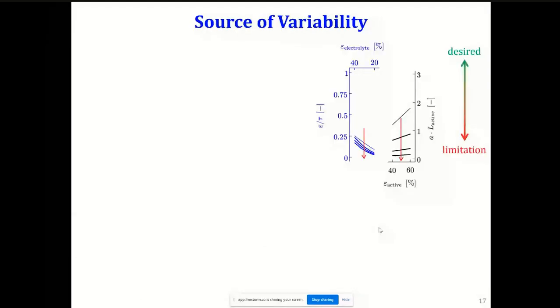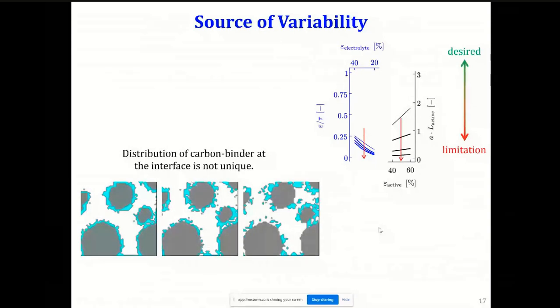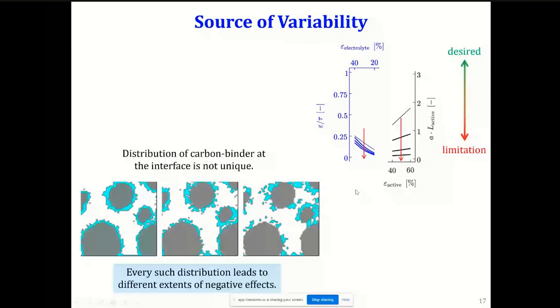Now, in all this calculation, there is a source of variability. And the variability comes because this distribution of carbon binder phases at the interface is not unique. Depending on how you prepare, depending on your electrode fabrication conditions, this is going to change quite a bit. Thankfully, the part that we are certain about is that it will contribute negatively, and it's going to have more and more detrimental effects if we let in more and more carbon binder phase. So it gives a general guideline of what to look for. And then if you have specific data, then you can go back and construct those resistance maps for the particular electrode that you're preparing in your lab or in your company. And then you can do even more accurate design of these electrodes.